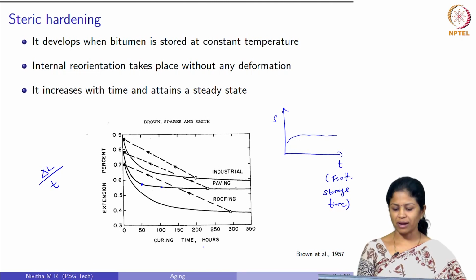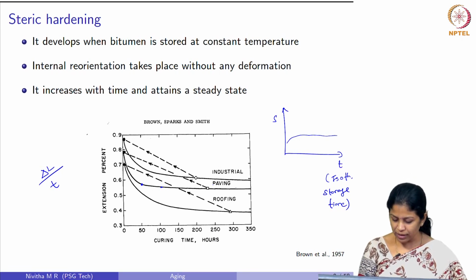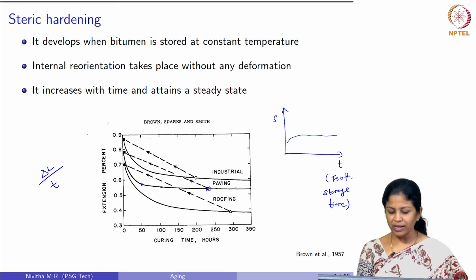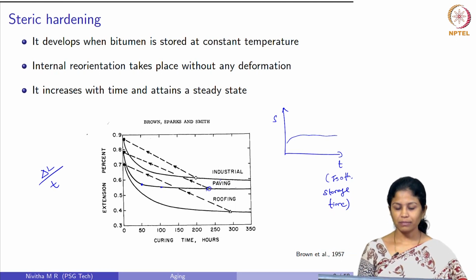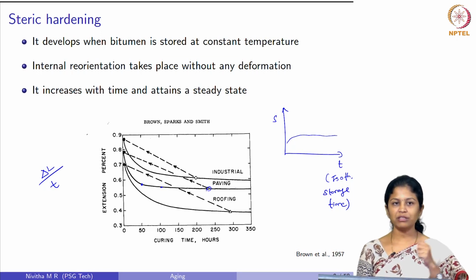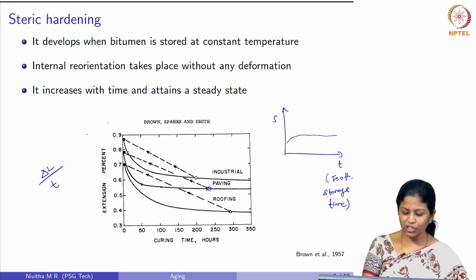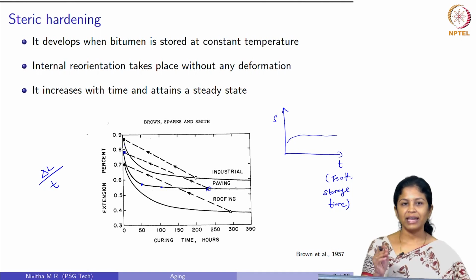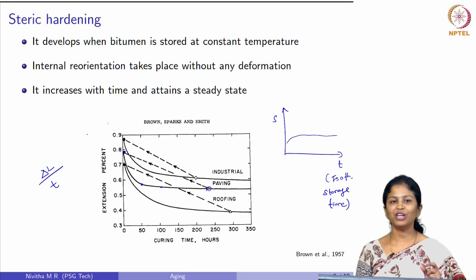Now, what they have done is that after they have cured it for 220 hours or so, they tried to heat the material, right. So, once this material was heated, this time is now reset to 0. At 0th time they have again measured the extension percentage. You can see it has reverted back to this initial value. The same value was obtained after the material was heated.